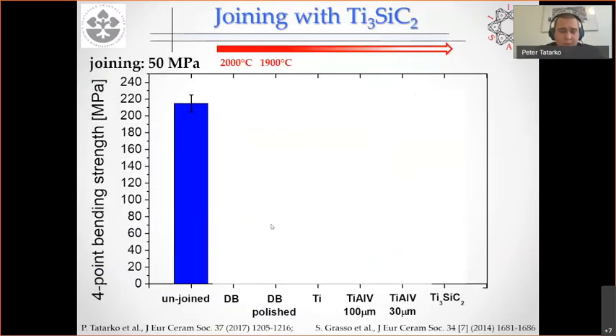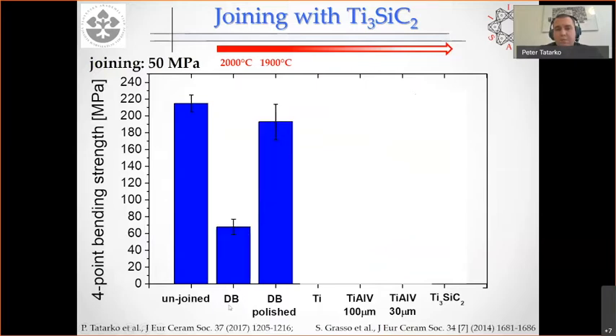So first of all, this is the bending strength of the reference unjoined sample. So it's a pure monolithic beta CVD silicon carbide. The strength was around 220 megapascals. And then we tested the joined samples: this is the direct bonding unpolished sample. This is the direct bonding polished sample. So you can see that especially for the polished sample, we got quite a good strength. It reached almost the initial strength of the reference material.